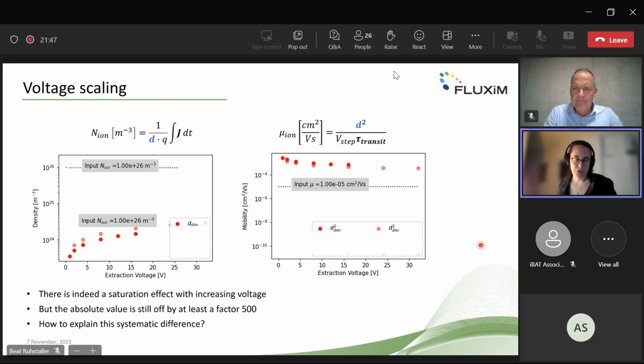So here what we show is that also in the simulation, we do an increasing extraction voltage sweep. Basically, the motivation was, again, to move as many ions also in the model as possible. And you can see on the left-hand side, the extracted density from the integral, from this formula above here, if we use the device thickness, and the comparison with the input, because